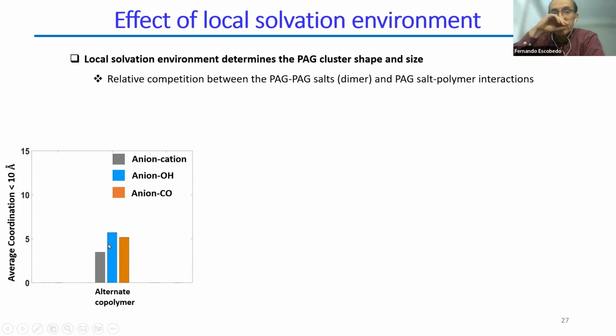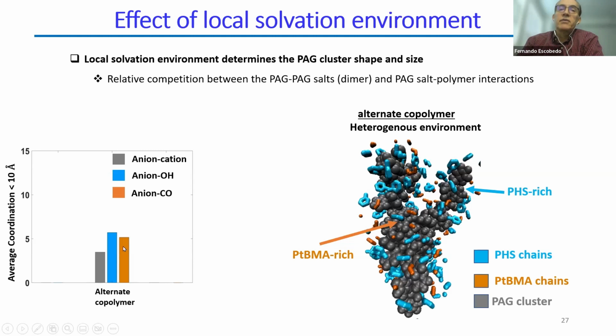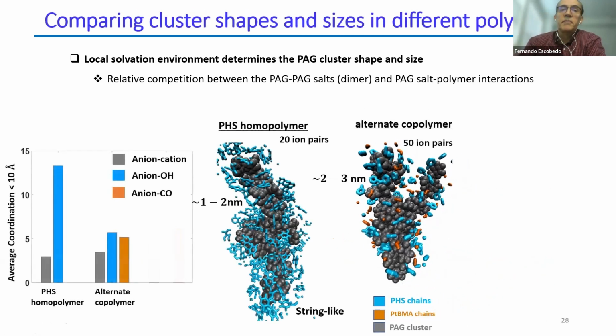And this is what you will see for the alternate copolymer, this average coordination within a distance of 10 angstroms. I can show how this looks. With the corresponding colors, you can see the polar groups of the polymers around this cluster of salt ions. What you would like is to reduce this brown box, make it smaller, and make the sum of the other two larger. That's exactly what you see if you use just a PHS homopolymer. You see that this gray bar is now smaller, and the height of this is taller than the sum of these two. So this is in some ways an ideal scenario, and you can see pictorially how that looks. It's better solvated.